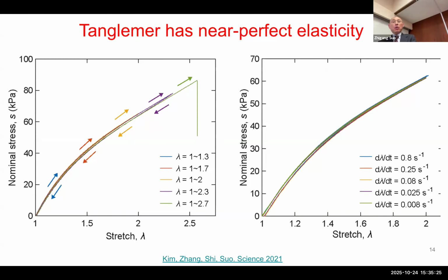All right. So now for hydrogel, people always have the impression that the polymer is highly hysteretic because the chains rub against each other. For this particular hydrogel, in between the chains you have water, and water has extremely low viscosity. So we ask the question: if you have entanglement, does the entanglement cause you problems and give you hysteresis? So we did this test.